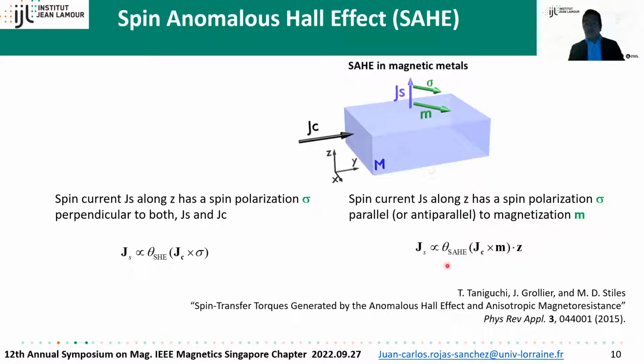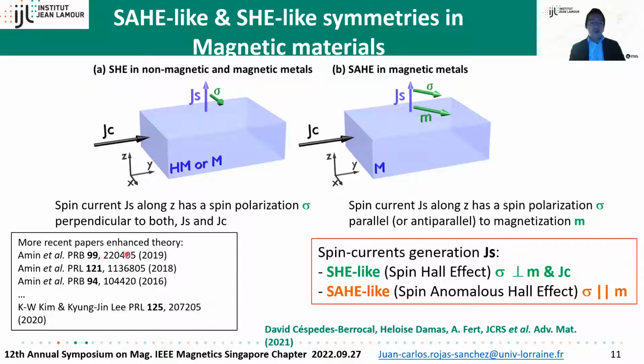Following this work, we call this the spin anomalous Hall effect, with an efficiency for that interconversion between charge current and spin current. We know the spin Hall effect with its symmetry in heavy metals such as platinum. However, more recently, a theoretical work predicted that magnetic materials with strong spin-orbit coupling also exhibit a spin Hall effect with a platinum-like symmetry.